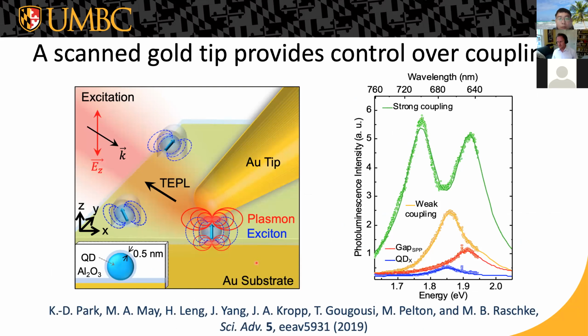No, that's a good question. So the quantum dots are quasi-spherical, but the underlying crystal lattice is not symmetric. So they have a zinc blende crystal axis, which has a preferred crystallographic orientation. So the transition dipole moments, I think, are believed to be oriented perpendicular to the c-axis of the crystal. So it's really the crystallographic orientation of the quantum dots that determines their dipole moments. Sure. Thank you.